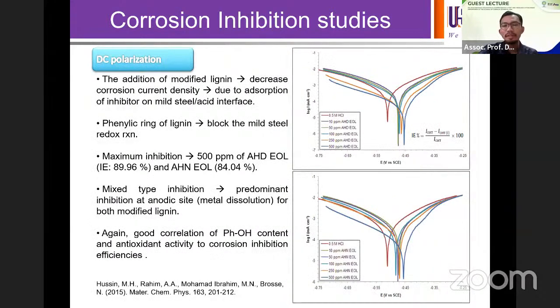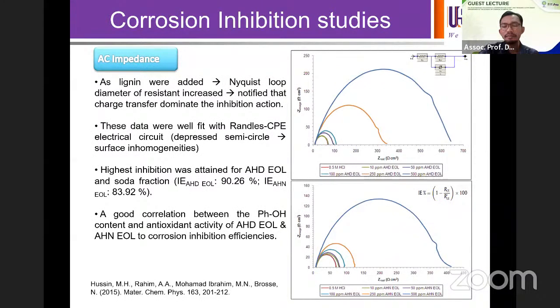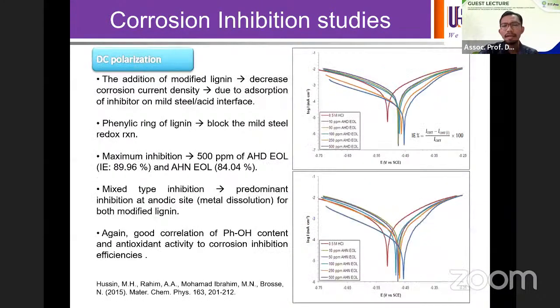And this is also supported with another technique, which is called potentiodynamic polarization. So before this, for impedance, we were measuring the charge transfer resistance, whereas in the polarization methods, we are measuring the current density values. And obviously, as we increase the concentration of modified lignin, the current density is reduced as well. And this gives us a better inhibition, which is almost 90%. This is in accordance with the EIS experiment that we did earlier.